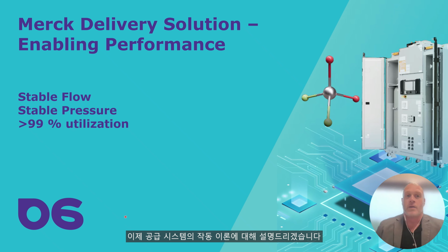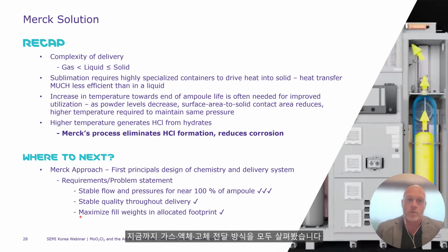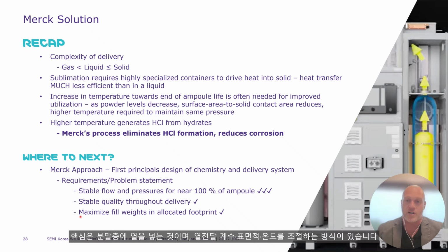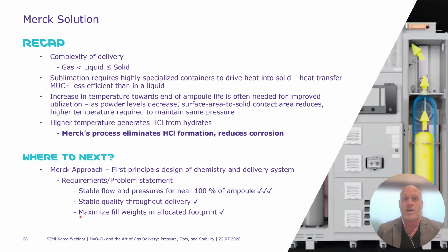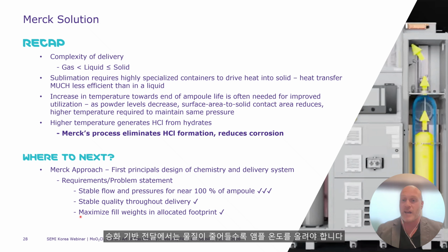All right. Now we're going to briefly go into the theory of operation for our delivery system. Quick recap, we went through gas delivery, liquid delivery, solid delivery. We talked about different strategies to sublime. It's really about driving heat into the powder bed, where you can change the coefficient, the area, or the temperature. In general, you need to increase the ampule temperature as you deplete in a sublimation scenario. As you increase that sublimation temperature, you're at risk of driving that hydrate reaction forward. You still have HCl pent up because you're not hot enough, and having HCl pent up means you're driving that reaction forward.